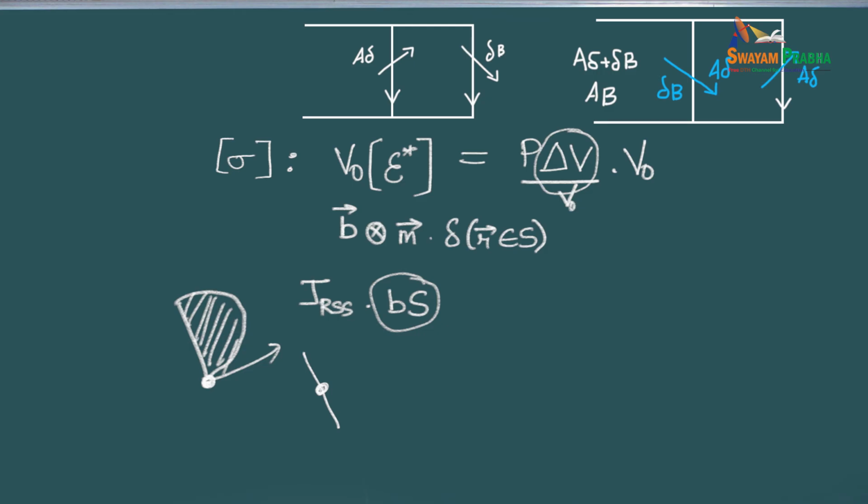Yeah, we hadn't talked about the Frank partial. So the Frank partial is this one here. It is along 111, and it forms with irradiation defects mostly. For me, the Frank partial is only seen as a result of irradiation. And this Frank partial can decompose into this partial plus that partial also. So you can have a decomposition of the Frank partial.